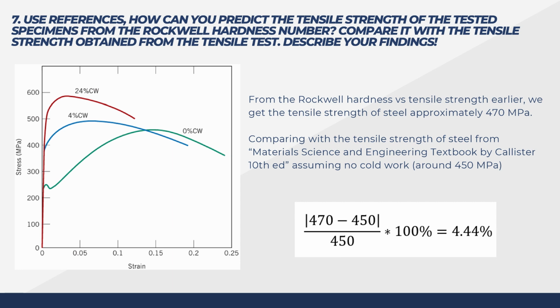Comparing to the tensile strength of steel from the Material Science and Engineering textbook by Callister, 10th edition, the tensile strength of steel from the stress versus strain graph is around 450 MPa. Comparing both results, we get a 4.44% error value, which I think is pretty accurate since we predict the tensile strength of the specimen only by using the hardness number.